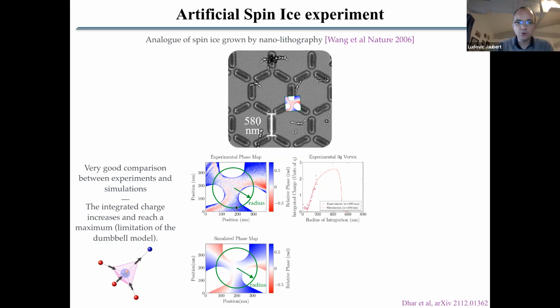And so we can draw a radius. And as a function of the size of the radius, we can integrate what's inside, and the magnetic charge that you have inside. And this is the curve that you have here. So the dots are the experimental data, and the solid line is the theoretical expectation from simulation. And you see that the integrated charge that you obtain increases linearly as you increase the radius. So that's the same thing that we have seen before with the tip of nickel.